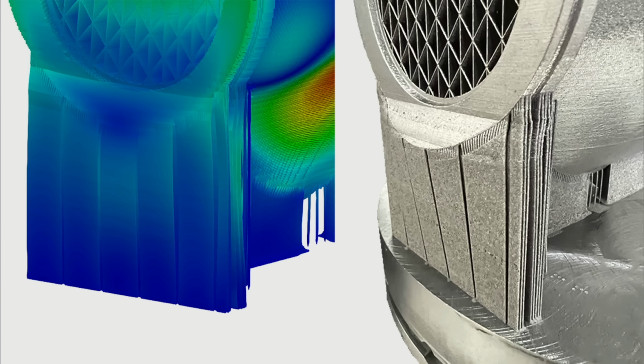So one thing that we had was when we printed the part, we supported this flange that started separately with supports that were parallel. You can see here, when we started building the flange, the whole support was able to flex and walk around, which would virtually scrap most parts. Being that this was our in-house test part, we were able to machine that back flat, but the back side of it is just as messed up as the front side. Fortunately, we only need it for clamping and not high pressure, so we were still able to use it.